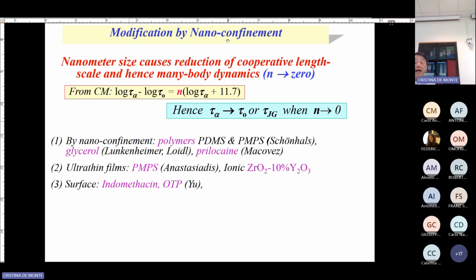Modification, nano confinement. For the coupling model, if you make the intermolecular coupling go to 0, when n goes to 0, then you can predict that the tau alpha at nano confinement will be just tau 0, which I can calculate from the coupling model, or tau JG right here. This is the reason why I can predict from the coupling model on nano confinement.